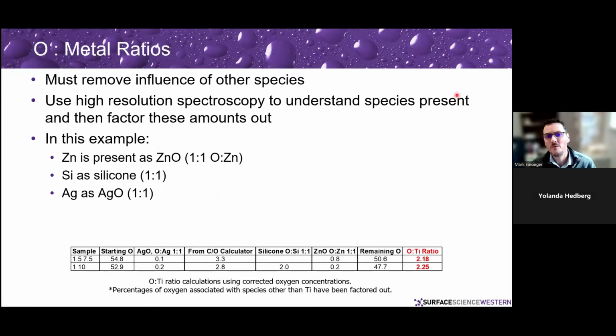And so we've got to remove the influence of oxygen from other species in order to make that kind of calculation work. If you do high resolution spectroscopy to understand the species that are present, you can then factor these sorts of things out. So the zinc that was present is a zinc oxide, 1-to-1 ratio. Silicon was present as a silicone, again, a 1-to-1 ratio, and silver as silver(II) oxide, again, a 1-to-1 ratio. And so you can factor those things out. And when you do that, you get a more appropriate titanium to oxygen ratio because now you're just looking at oxygen that can only be associated with the titanium.